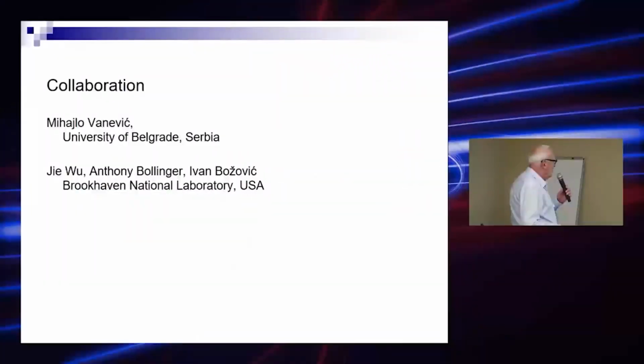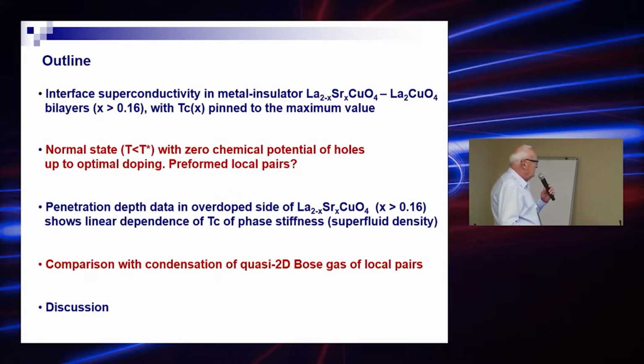This work is made in collaboration with Mihajlo Vanević from the University of Belgrade. He is now in the Netherlands, and by a group of Ivan Božović, Jay Wu, and Anthony Bollinger. I will present shortly two findings of Božović's group about interface superconductivity, overdoped LSCO, undoped LCO bilayers, and measurement of penetration depth and finding of linear temperature, critical temperature dependence of phase stiffness, of superfluid density.